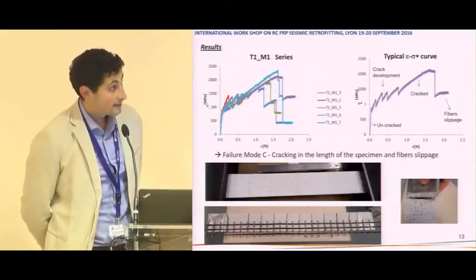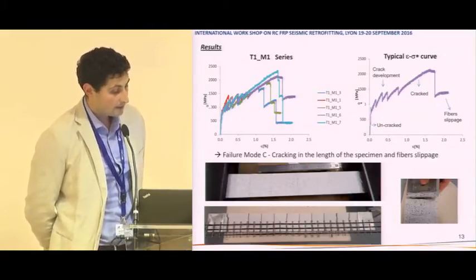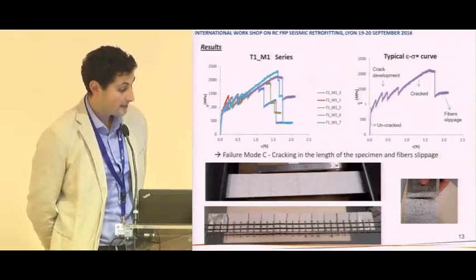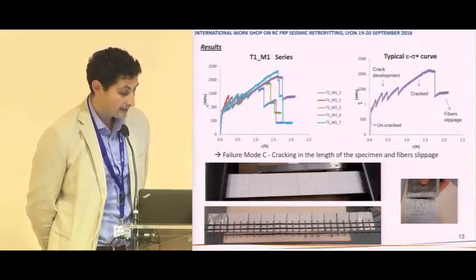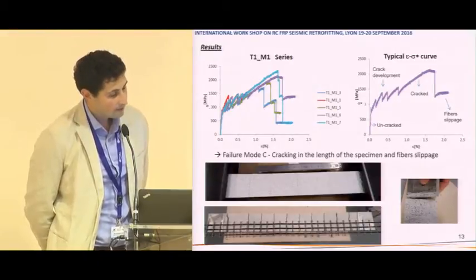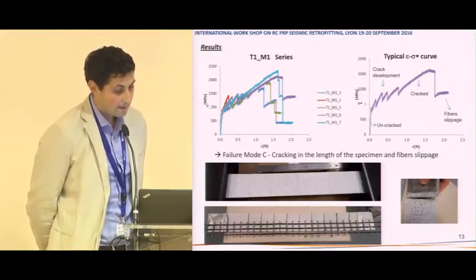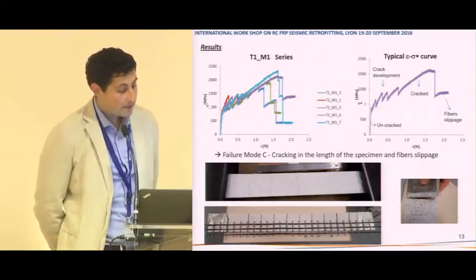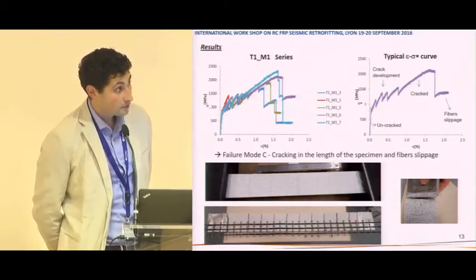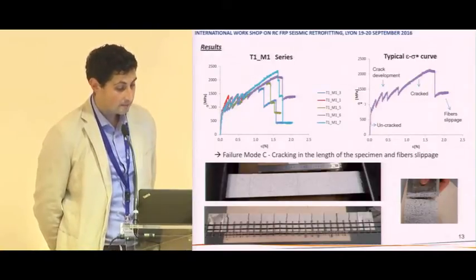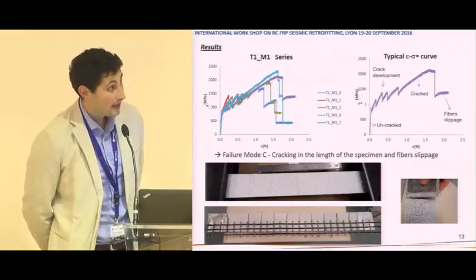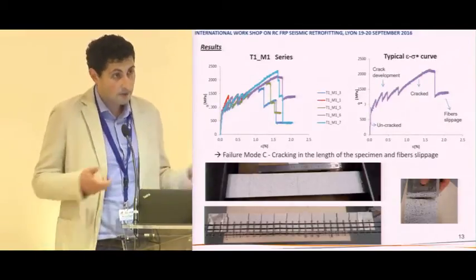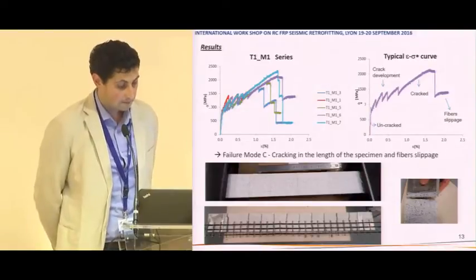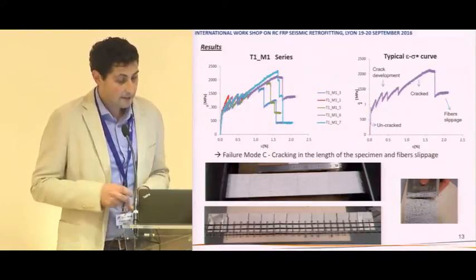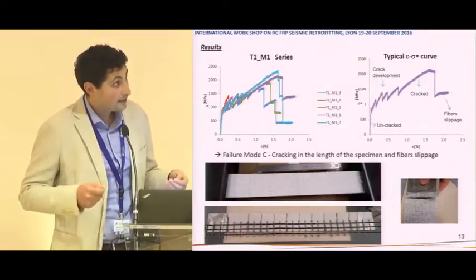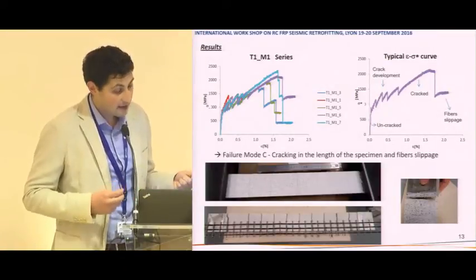You can see here the results. On the left, we can see that our results were coherent with a lower standard deviation. On the right, you can see a typical stress-strain curve characterized by the first 3 classic phases. The uncracked phase, where the composite works in an elastic manner, and this phase ends with the opening of the first crack.